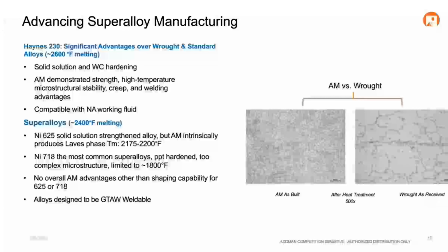When our customers were looking for nickel superalloys that had better performance, really driven by the hypersonics and launch community, we looked at Haynes 230. There's a lot to like there. One, from an ease of post-processing, it is solid solution strengthened. From a high temperature performance standpoint, it's primarily strengthened by tungsten carbides, which are inherently very thermally stable.